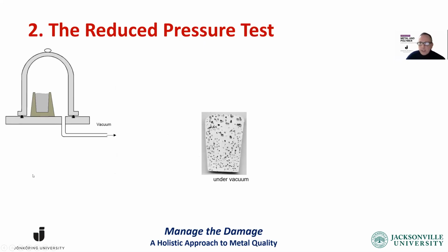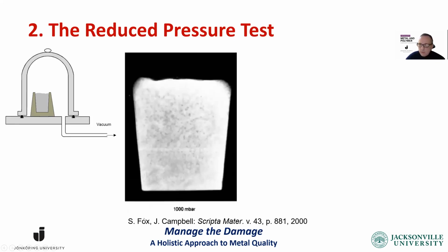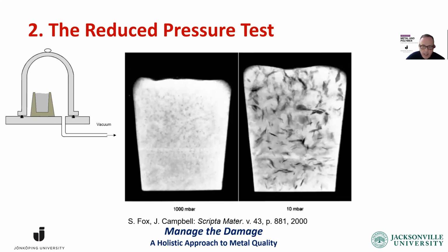So the reduced pressure test is the second one. As you know, we collect a sample, we put it in the chamber, we turn it on, there's a vacuum, the vacuum opens up the pores. And what we see here is classical work from 20 years ago. You see under atmospheric pressure, this sample, you're going to notice some gray areas in the middle. And when the pressure is reduced, the air entrained within the bifilms increases in volume. And as a result, we can see the real damage. And when you look at that, you can see the crack-like nature of the oxides, of the bifilms that get entrained because of the damage that has been given to the metal.